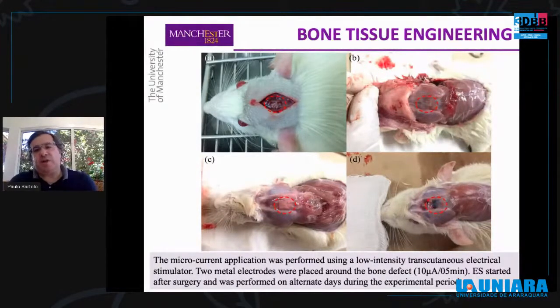And in this case, we explore the use of electroactive scaffolds and electrical stimulation to regenerate critical size bone defects created in the calvaria of rats. And we consider different routes. So one is the natural regeneration route, which was the reference for us, with and without electrical stimulation. In the second case, we filled the defect with polycaprolactone scaffolds, again with and without electrical stimulation.